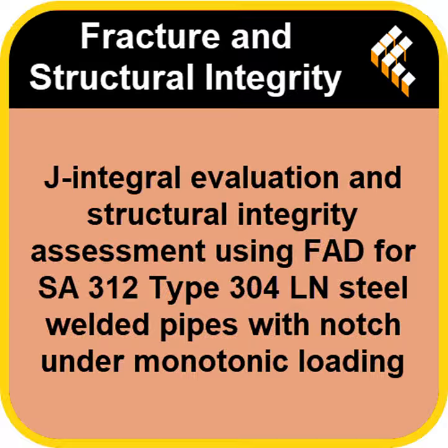But Takahashi's expression takes a more conservative approach. It's based only on the yield stress, the very first point where permanent deformation begins. So it ignores any strain hardening benefit. Correct. It essentially assumes failure occurs much closer to the initial yield point. This immediately led to lower predicted limit load moment values because it predicts failure capacity was reached earlier.